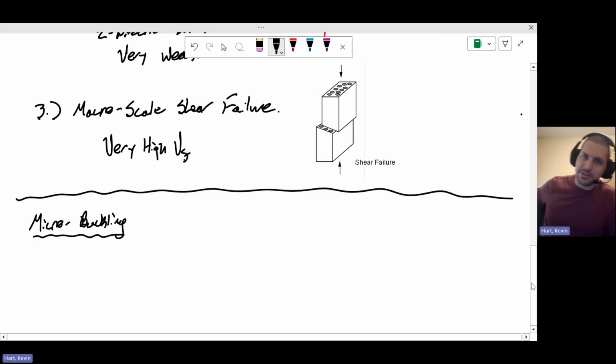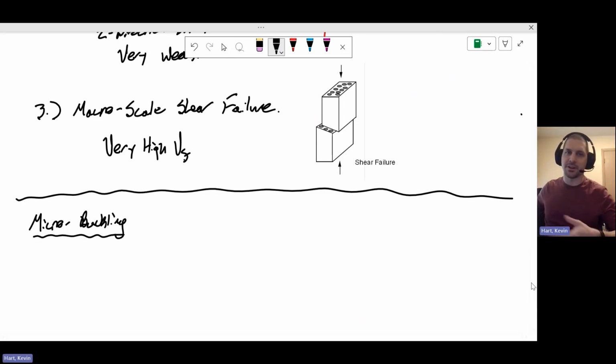Okay, like I said, there could be two different ways that this could happen. It could be in phase or it can be out of phase. And the math associated with those two are quite different because whether or not the fibers can communicate with each other side by side plays an important factor on how much load you can allow before buckling happens.